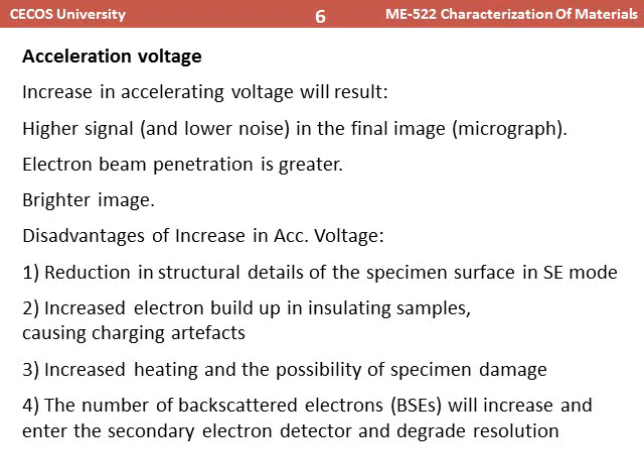So by increasing accelerating voltage, we are compromising the fine quality image of secondary electron mode, because we are reducing the structure details of the specimen surface. Why is this happening? Because the high energy electrons can penetrate to greater depths. If they penetrate to greater depths, then there is a compromise in acquiring secondary electrons from the surface of the specimen.